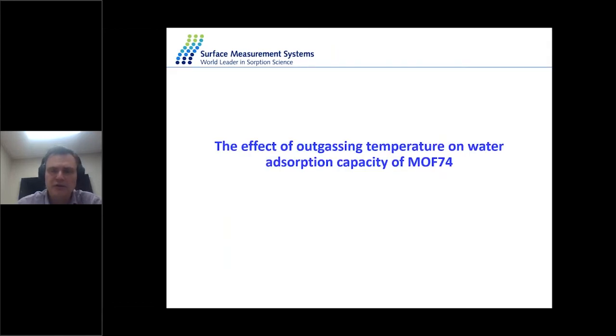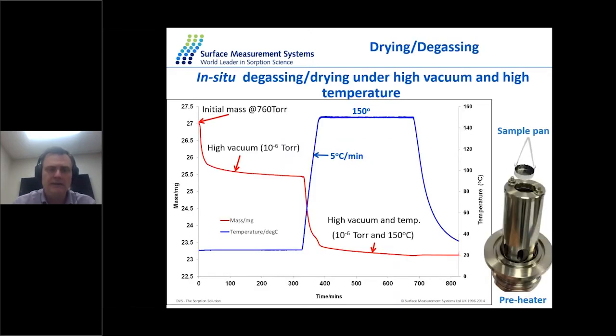Now I'm going to briefly talk about the effects of outgassing temperature on water adsorption capacity of MOF 74. And so I want to spend a couple of minutes on the outgassing. Outgassing is quite important for metal organic frameworks, and the selection of correct outgassing temperatures can have profound effects on the absorption capacity. So if the outgassing temperature is too low, for a thermally stable material, you can actually get incomplete outgassing. If the temperature is too high, you might destroy the material.